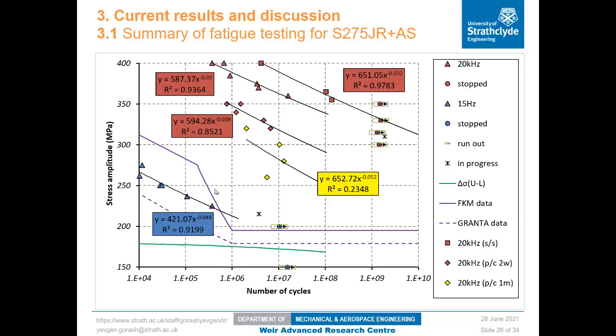Then the next group are the data points obtained at low frequency of 15 Hz. And the purpose of this data is to investigate the effect of frequency. So that has been done by finding the difference between triangles, the data obtained at 20 kHz and the data obtained at 15 Hz, and this difference in average is roughly 170 megapascals. So that's the green line.